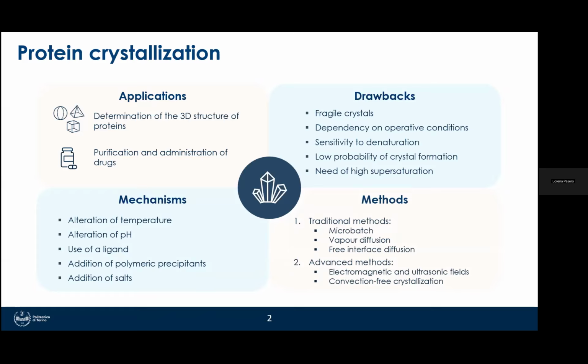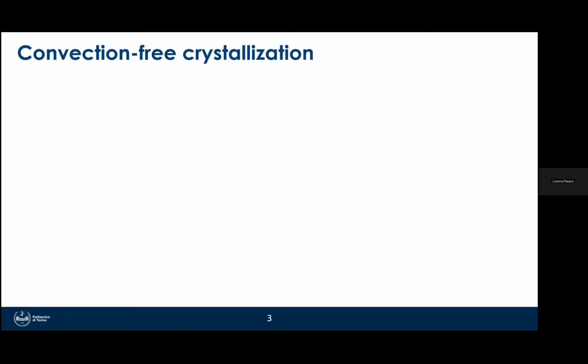And we can induce nucleation through different methods. The traditional ones, which are microbatch, vapor diffusion, and free interface diffusion, are commonly used, for example, for screening. And there are more advanced methods, which rely on electromagnetic and ultrasonic fields, and on convection-free crystallization, which of course is the topic of this presentation. So regarding convection-free crystallization, this is used to eliminate the convection and ensure transport through diffusion. This can lead to controlled supersaturation gradients and to a more uniform crystal growth.